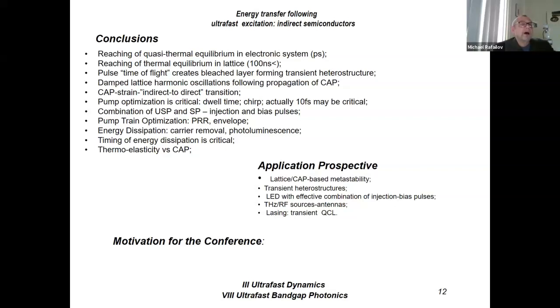So coherent acoustic phonons and the strain initiated by them provide the indirect to direct band gap transition, a huge technological advantage. So pump optimization is really critical. We can work with dwell time, we can work with chirp. Ten femtoseconds is pretty much critical if we're talking about the excitation process.